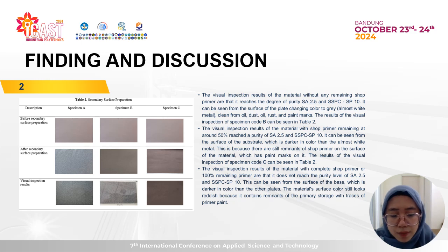And for specimen code C, the visual inspection result is that the material with shop primer remaining at around 50% reaches a purity of SA 2.5 and SSPC SP10. It can be seen from the surface of the substrate, which is darker in color than the almost white metal. This is because there is still shop primer remaining on the surface of the material, which has paint marks on it.